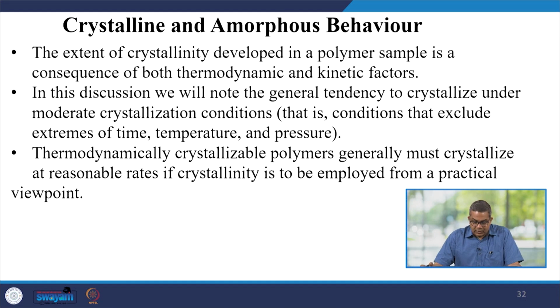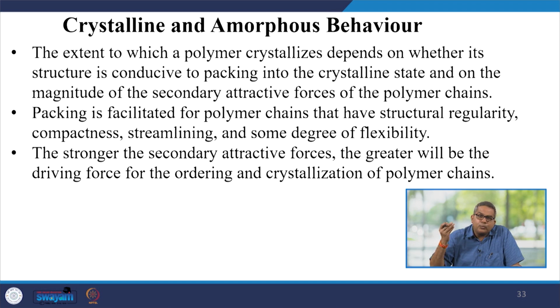The extent of crystallinity developed in a polymer sample is a consequence of both thermodynamic and kinetic factors. We will notice the general tendency to crystallize under moderate crystallization conditions, that is, conditions that exclude the extremes of time, temperature and pressure. These three are the most important variables. Thermodynamically crystallizable polymers generally must crystallize at reasonable rates if crystallinity is to be employed from a practical viewpoint.